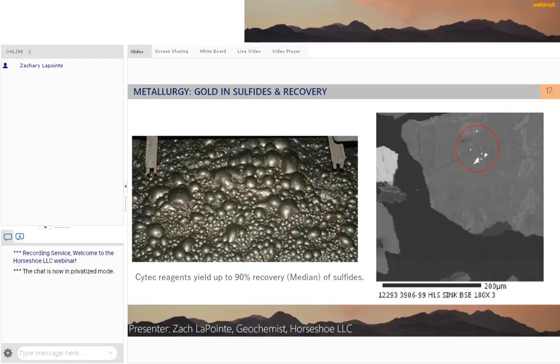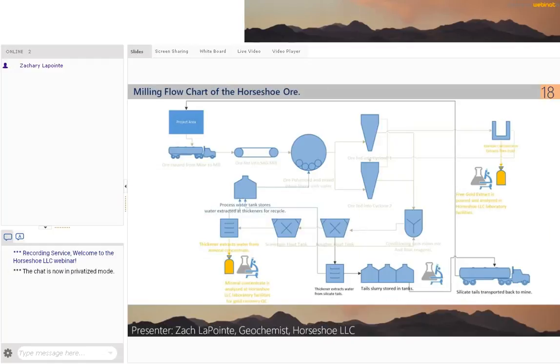So I'll walk you through our mill workflow now. Again, our mill is a sulfide froth flotation system, and we deliver ore from our project area to the mill site via truck, where we introduce our ore and water into a SAG mill. This is where the ore undergoes 20 to 40 minutes of grinding so we can reduce our ore to a 180 mesh particle size.